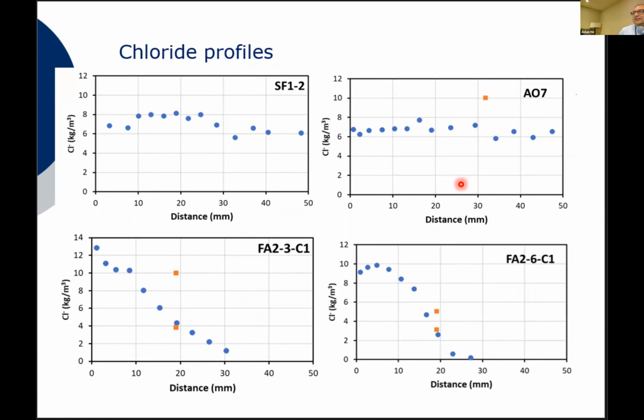So these are examples of the chloride profiles, and as I told you, in this case, we did do some electromigration. The rebar depth in this case was 19 millimeters. And unfortunately, the corrosion, I'll show you in a moment, covered most of the length, so we don't have a value at the rebar trace.